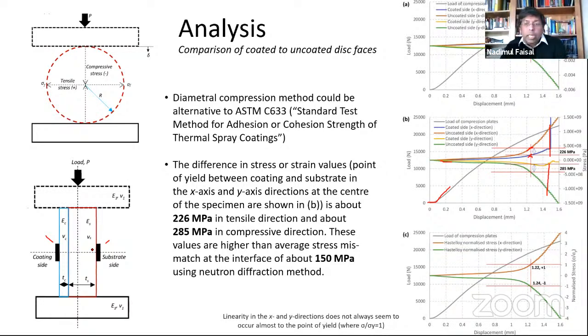So you can have a relative strain mismatch, which can be investigated using this method. And this could be an alternative method if you compare with a standard adhesion method, which is used in thermal spray coating. And we compared these data with the neutron on the same material, and the results were way off because there are two different techniques, but it would make sense if we investigate more. So if you want to have a look, you can have a citation of this work.